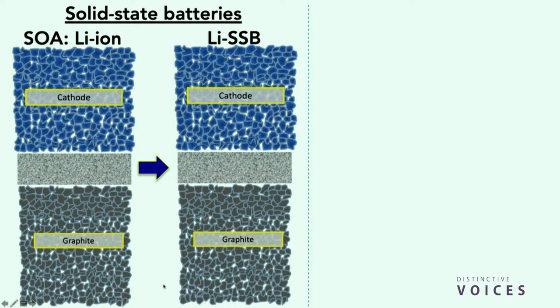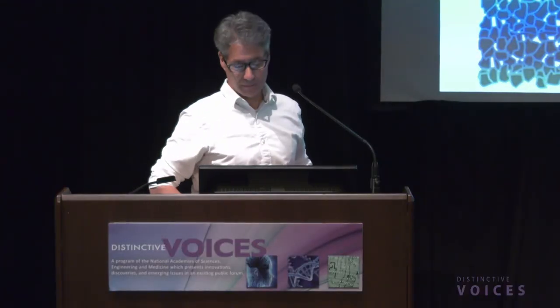Okay, so what if we can go back to lithium metal? And how do we do that? It's just a brute force technique. There's a lot of elegance in terms of the materials discovery, but physically, it's just that. Don't let those tree-like structures form in the first place by physically squashing them with a solid electrolyte.